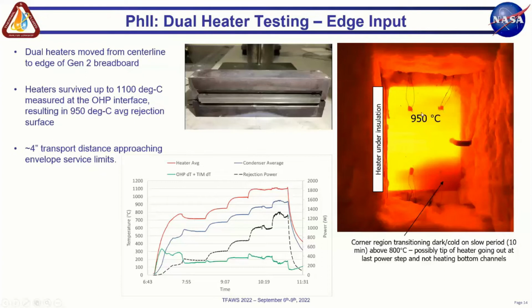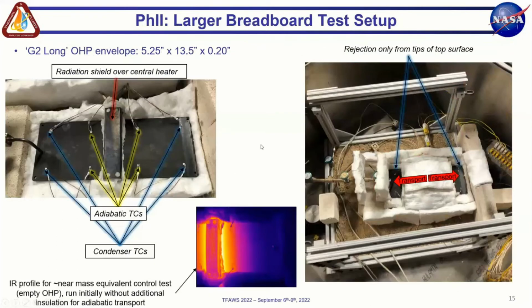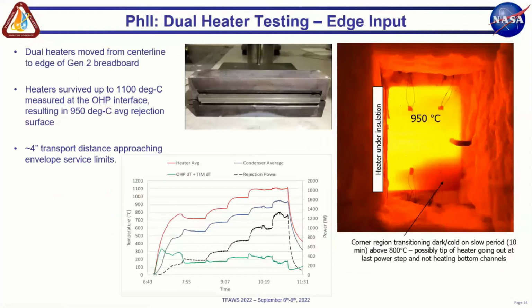So this was a really nice test. We're actually starting to approach the envelope surface temperature of that Inconel 625 envelope. The vapor pressure of the fluid inside is actually quite low, as is the nature of the liquid metals in this temperature range. So not at risk from a factor of safety to pressure containment, but just out there where the yield strength of 625 has really fallen off the cliff. So that's where we pull the plug on pushing the temperature. All right, so yes. We got about 3 minutes left.